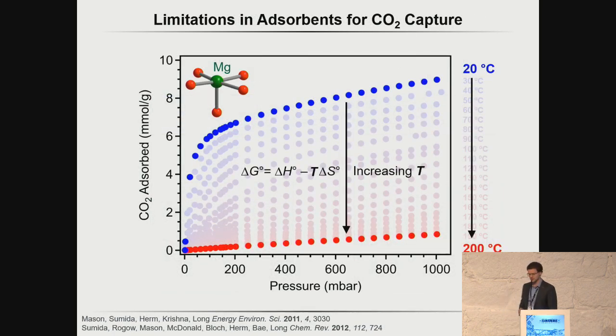I have shown here plots at variable temperatures of gas carbon dioxide binding to the open coordination site in magnesium MOF-74. At modest temperatures of 20 degrees Celsius, we have steep uptake. We have a lot of carbon dioxide that is binding to this Lewis acidic metal site. But the challenge is, as we increase the temperature, we are going to make binding more entropically penalized. And you can see here, these isotherm profiles start flattening out as we go from 20 degrees Celsius to a harsh 200 degrees Celsius. And really, at the start of our work, this was the state of the art for adsorbents performing at high temperatures.